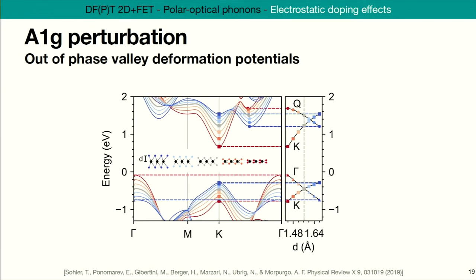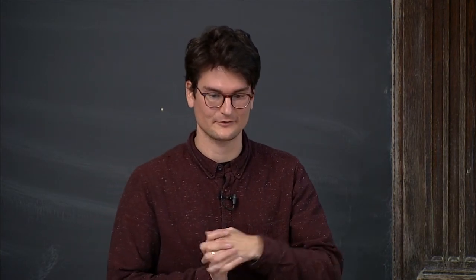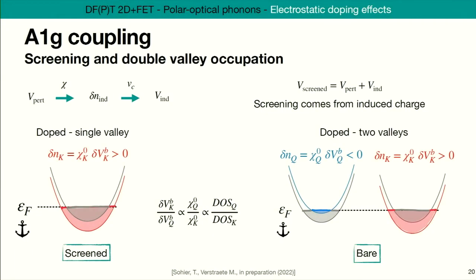The second step is understanding what this means in terms of screening. We come back to screening a lot, but it is quite essential in electron-phonon interactions. The basic principle of screening is that you have a potential perturbation that will induce a variation in the charge. This induced charge will then induce a potential, the induced potential. And then the screened potential is the sum of the perturbation and the induced potential. So in this story, you realize that you really need some induced charge. If you have no charge induced, you have no screening. And this is what happens here.